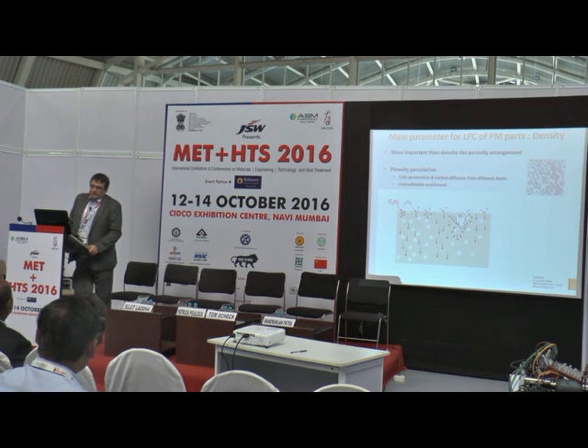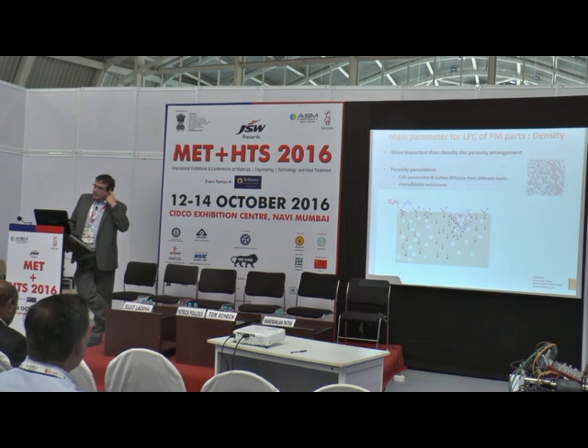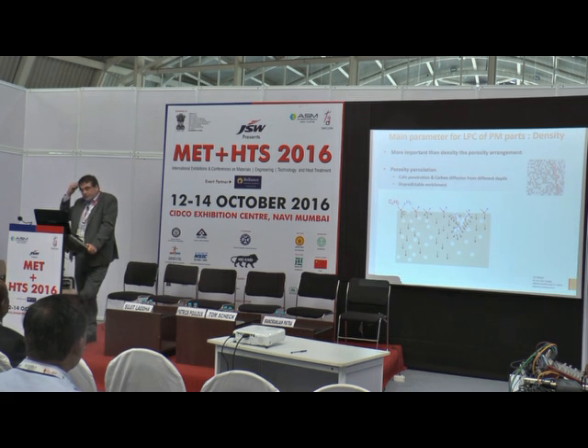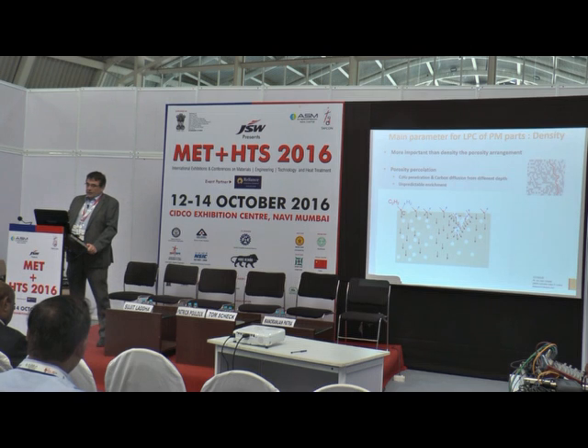So the issue we may have with sintered parts is the porosity, and even more than porosity, it is difficult to have homogeneous case depths. This is a percolation network. It means that if the pores are connected together, then obviously the carbon will diffuse faster to a certain depth than at the surface. Because also the surface will be bigger, so we may have discrepancies in the case depths.